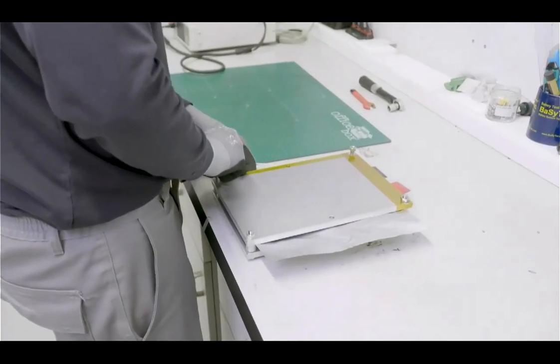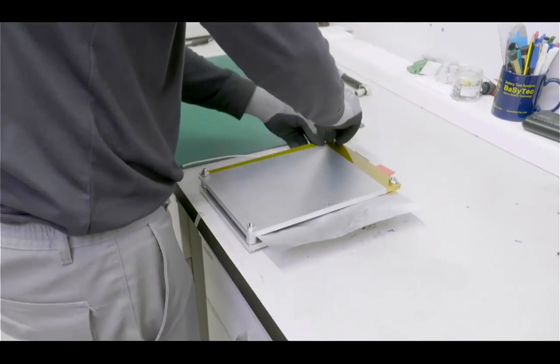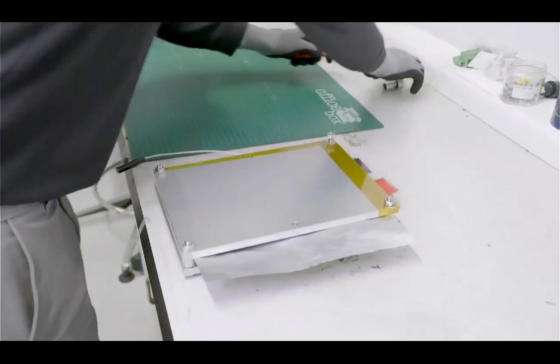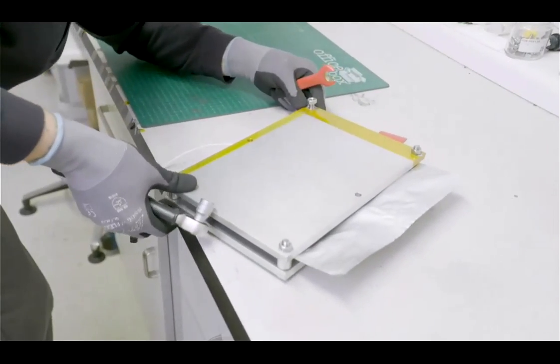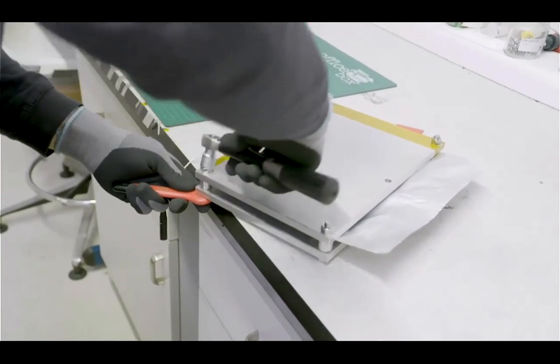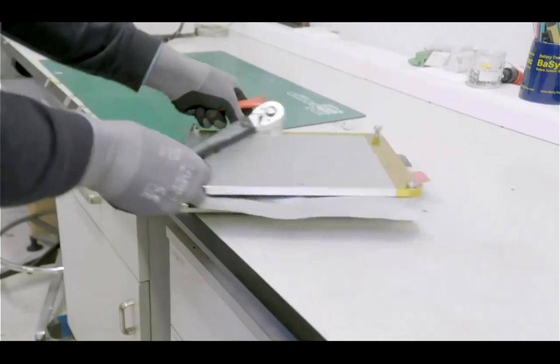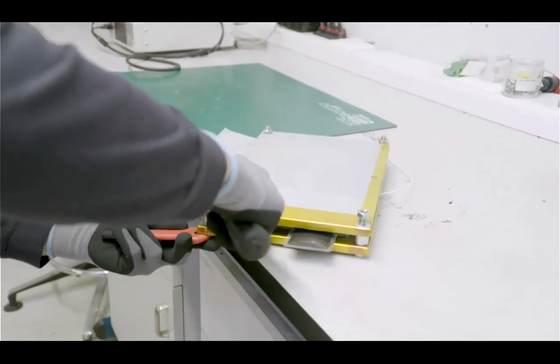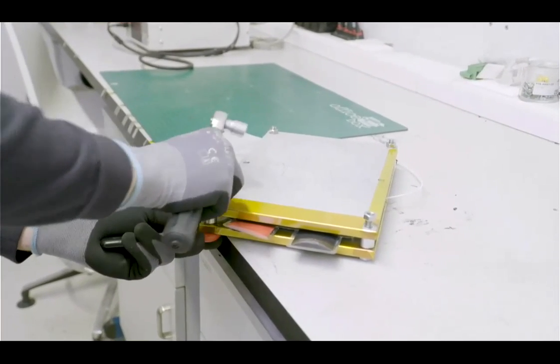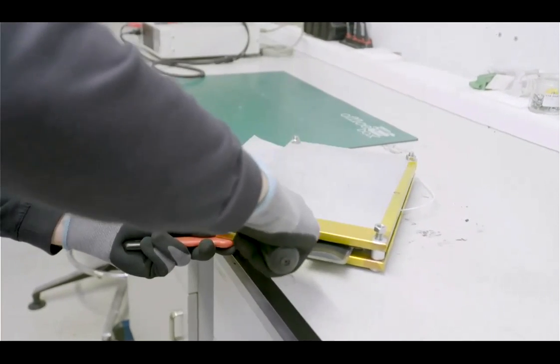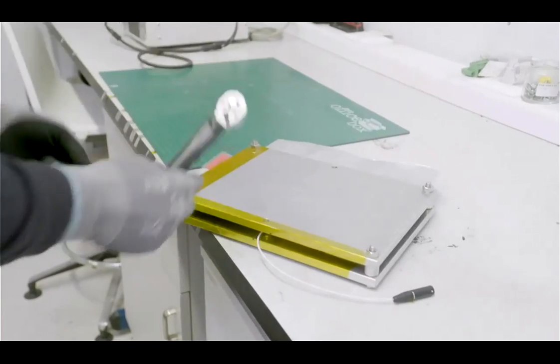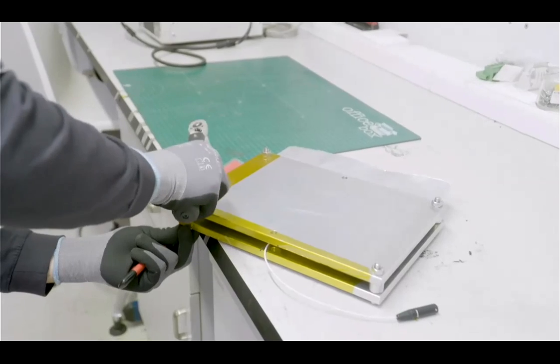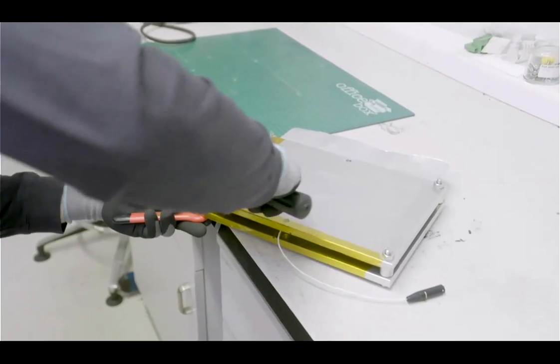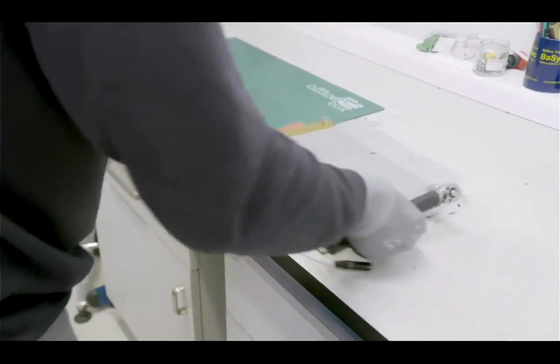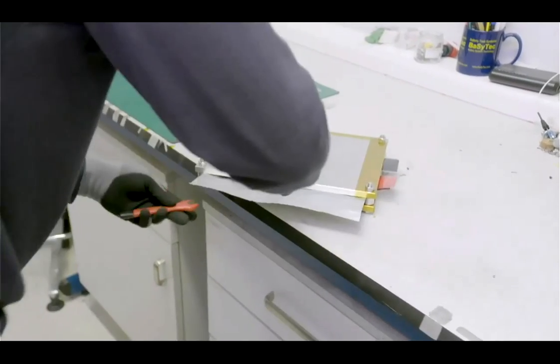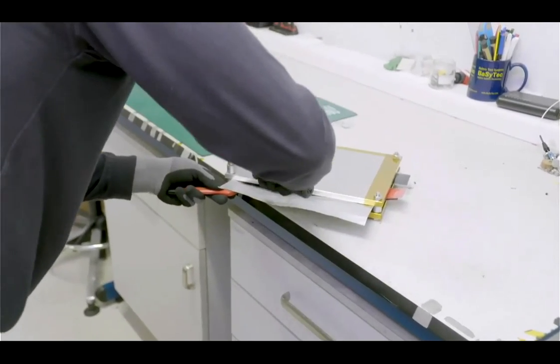So for formation, the cells are charged or discharged following a very defined current and voltage curve. So during the formation, the lithium ions are diffused to the graphite on the anode side, and we are forming what is called the solid electrolyte interphase. This is an interface between the electrolyte and the electrode. During the formation of this solid electrolyte interphase, some electrolyte will be degraded and it will generate some gas. So the gas that is generated during the formation will be accumulated in the excess part of the pouch foil.